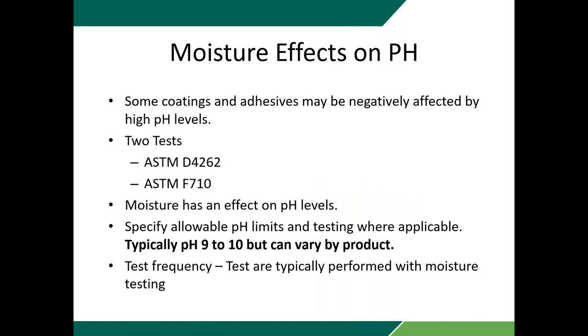Now, another thing I talked about a minute ago that affects coatings and adhesives is pH level in the concrete. Concrete is naturally high in pH, and the water, when it's moist, can increase that pH. So there's two tests that are run for that, and they're both fairly simple tests, in which they're using strips or phenolphthalein or something along that line, and they're basing it off of a color that they see in the test in the solution at the surface.